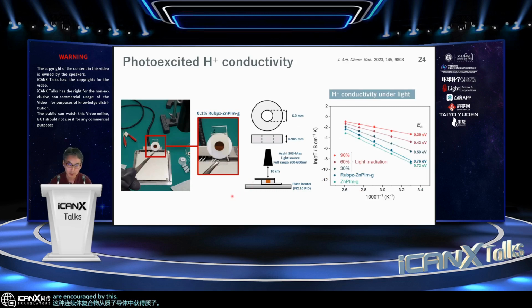Encouraged by this behavior, we fabricated the membrane of the glass as shown here, which is about 6 millimeter in diameter. And then we shed the light by changing the power as in this scheme, okay? And we conducted the ion conducting measurements, and the results are shown here. So the pristine glass with dopant shows this proton conductivity. But if we shed the light irradiation with different power, the proton conductivity dramatically increased. So this may suggest that the dopant and glass matrix has a switching behavior.